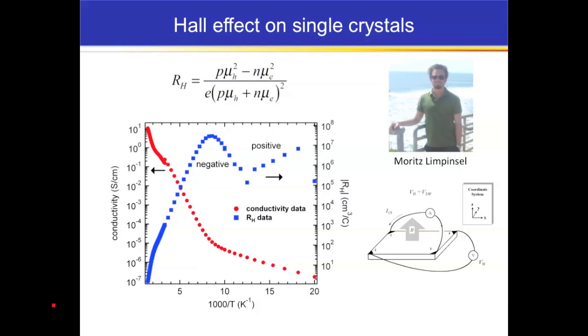But the Hall coefficient, the blue data here, is pretty strange. It's N-type, so it's negative above this point here. So at this higher temperature, we have an N-type material. Then the Hall coefficient goes through 0, and then it switches sign and becomes positive at low temperatures. And again, like I mentioned, this is pretty weird behavior. So let's try to explain this. Let's first look at the conductivity. So I'm just going to extract this red curve out here.